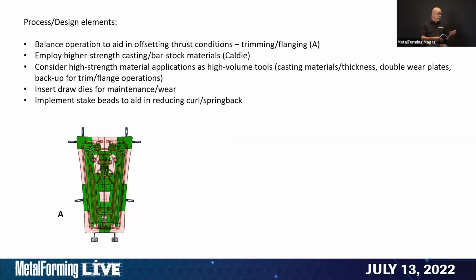Now, if you use an A2 or a D2, which tempers at like 550 degrees Fahrenheit, when you apply the PVD coating, it's actually going to make the tool softer. So tool steel selection becomes really important when we're looking at inserting dies for high strength applications.